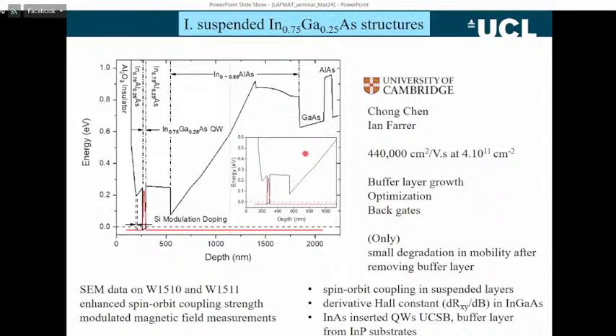This is the surface on the left-hand side. We put down an insulating layer on the surface. We then have a so-called quantum well, where the red line is the wave function. So the charge is just confined to a very, very thin two-dimensional sheet. Then we have the buffer layers, and we have this strongly graded layer.